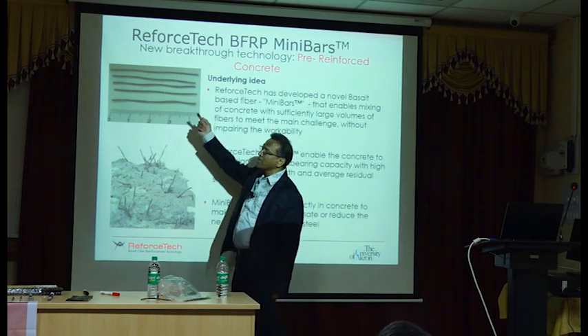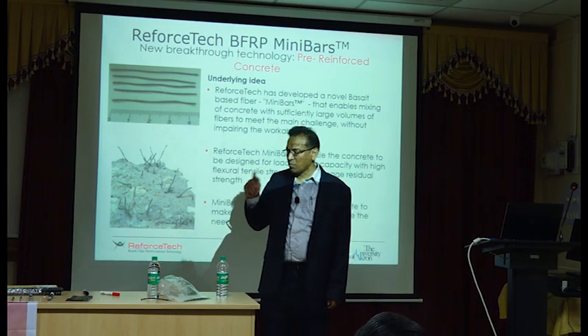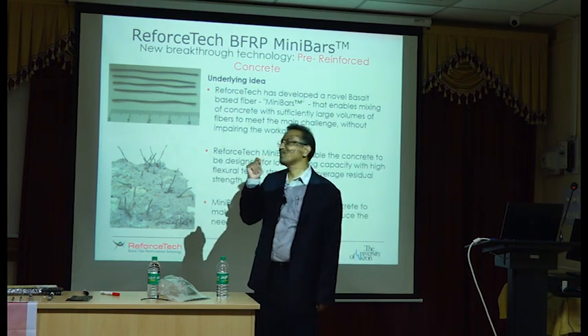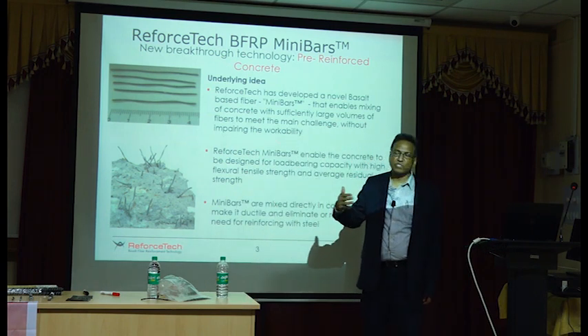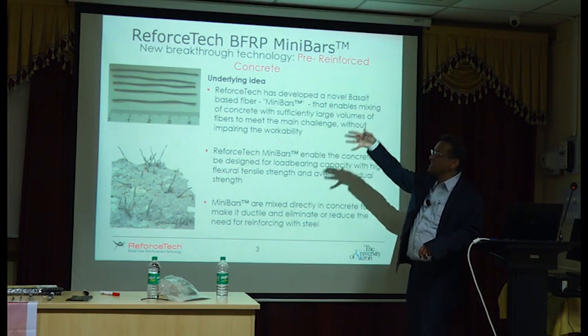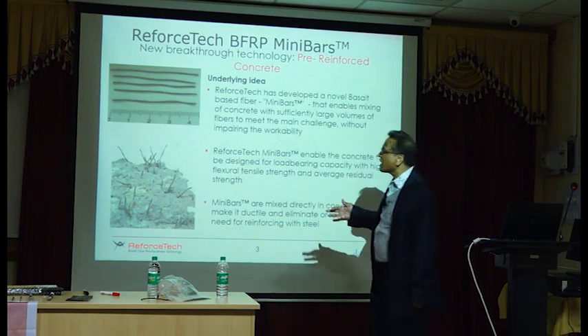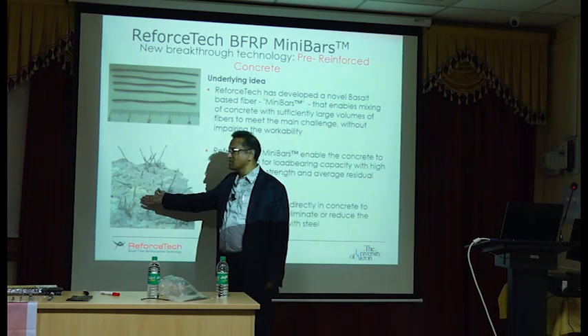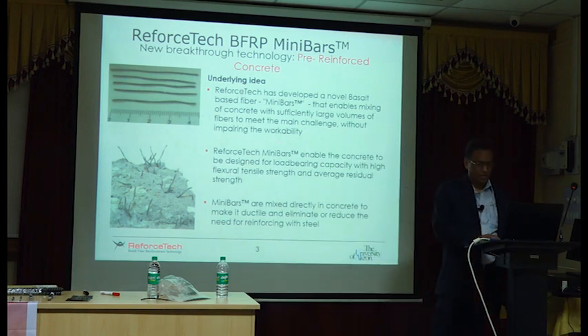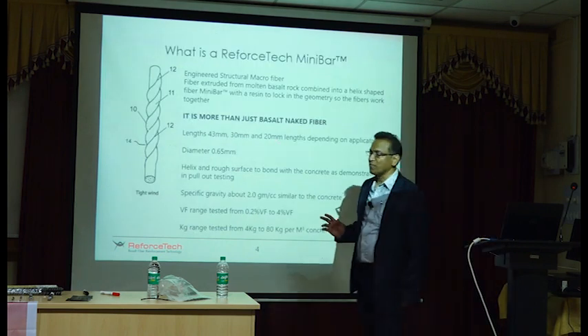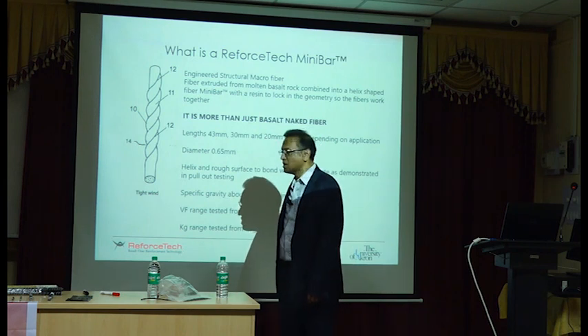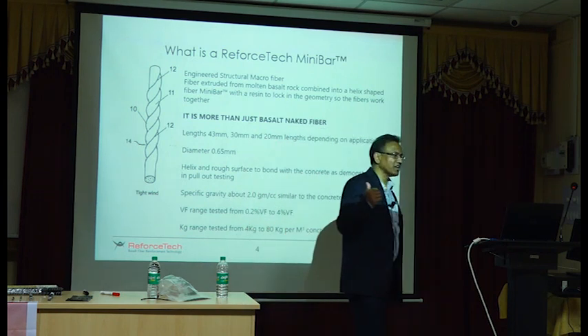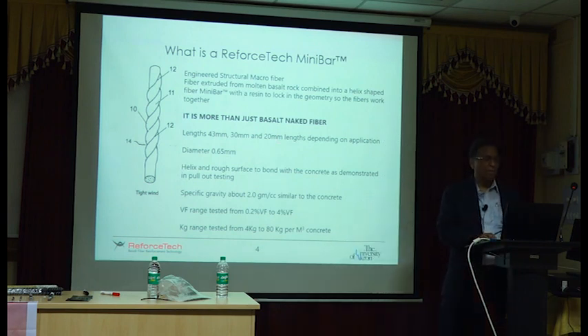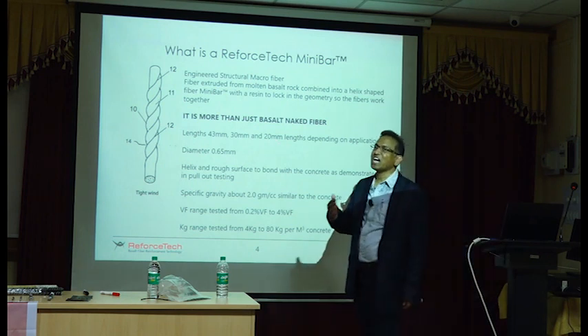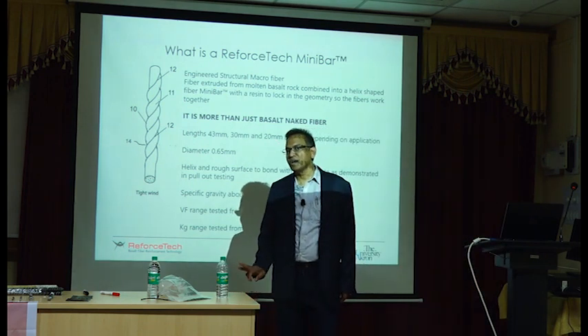So this minibar product is nothing but an FRP bar at a very small scale, put it that way. And it will be mixed just like in fiber reinforced concrete, just like your polypropylene fiber. You mix this in the concrete mix and then make the concrete. When you break it, it looks like this. Very nice product, very good product. So the residual strength for this kind of material is very, very high compared to say polypropylene fiber or other non-metallic fibers. Metallic fibers give you very good residual strength, but non-metallic fibers you cannot even mix in large quantities. That's the difficulty with non-metallic fibers.